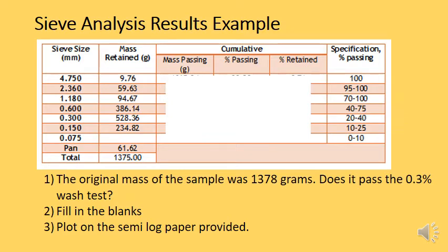So we need to do a wash test here to make sure that the final weight is not too different from the original weight. We need to make sure that the final weight is no more than 0.3% different from the original weight. So there's a calculation you do there. It's 1,378 minus 1,375, so 3, over 1,378, and that should give you a percentage.